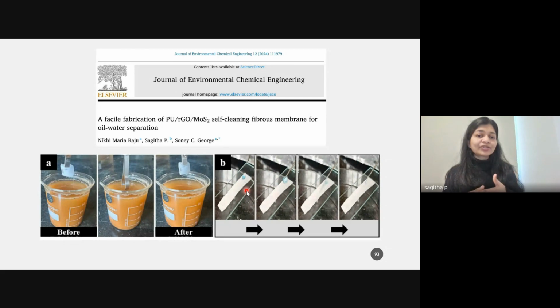So as I discussed, reduced graphene oxide has a hydrophilicity lesser than graphene oxide and higher than graphene. So reduced graphene oxide can also be used for making some kind of super hydrophobic surface. Polyurethane is a hydrophobic polymer. When we incorporated reduced graphene oxide and molybdenum sulfide into the polyurethane matrix, it helped to increase the hydrophobicity of the polyurethane matrix, and it made a super hydrophobic surface. So when we dip this polymer in the water solution, what we have seen is that this material is not getting wet by water.